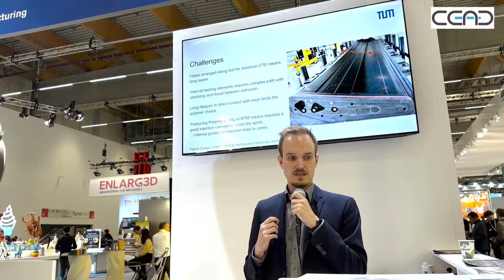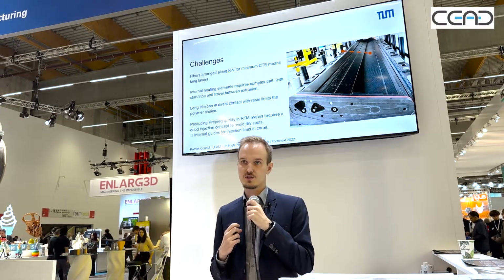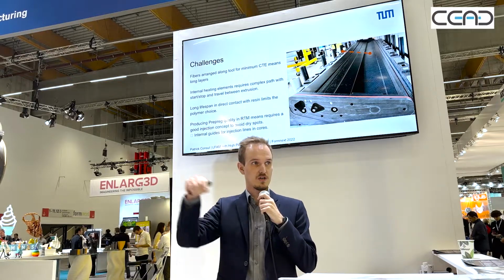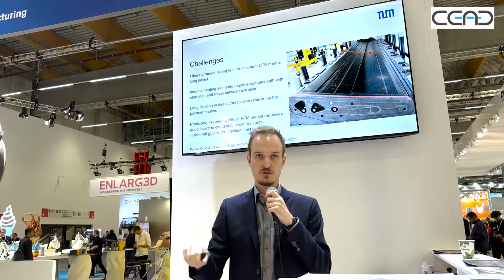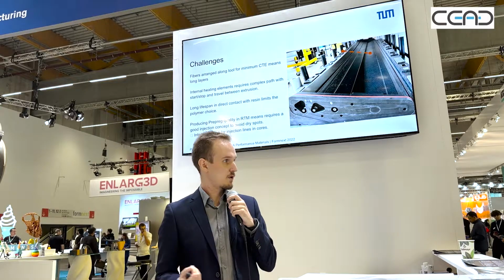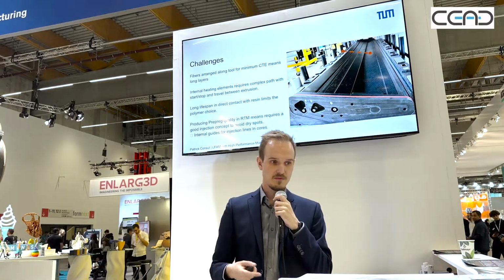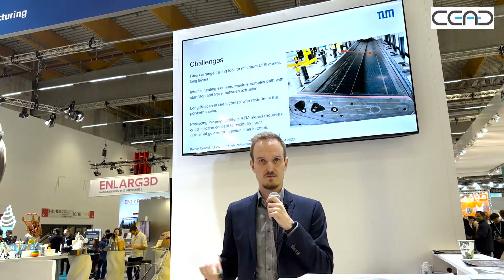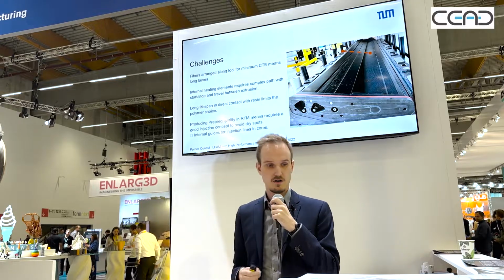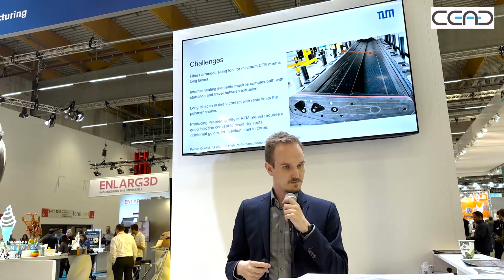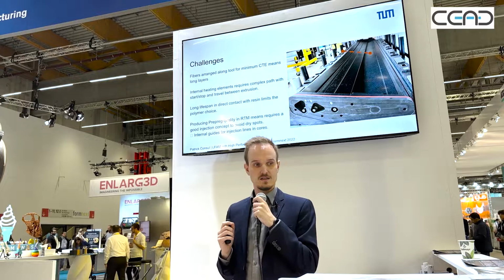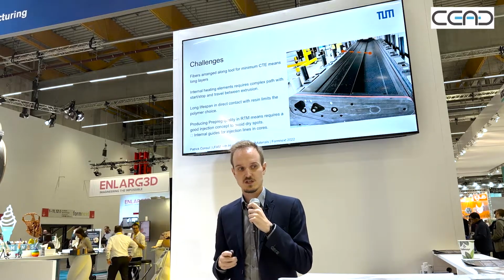The internal heating elements meant we had a lot of start and stop. We had travel moves in between individual print segments, where the melt pump from CEAD really helped us get that printed without oozing everywhere. And the long lifespan in direct contact with the resin is actually why we chose PEEK.